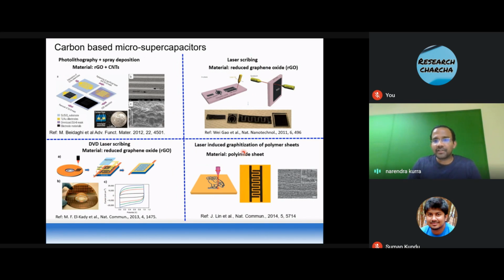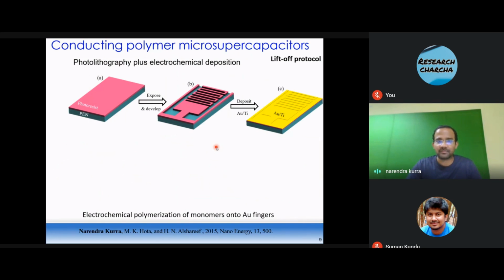And there are other studies where laser-induced graphitization was exploited in making micro supercapacitors. You start with a polymer, which is an insulating substrate like Kapton, and the laser irradiation carbonizes and graphitizes those irradiated regions into graphitic patterns as shown here, and you build micro supercapacitors out of it. So there have been a lot of works on photolithography as well as direct write methods in making micro supercapacitors.